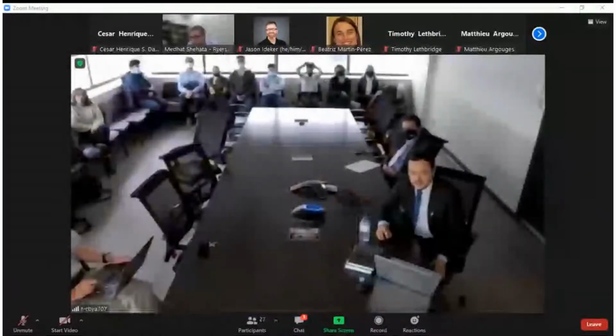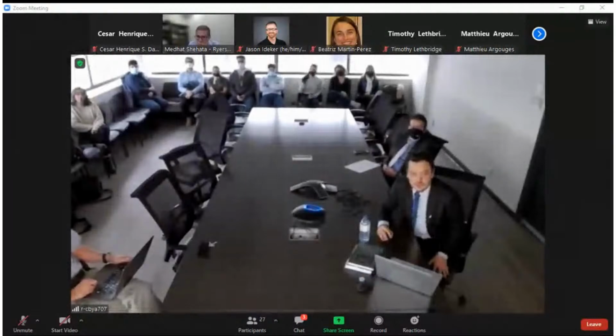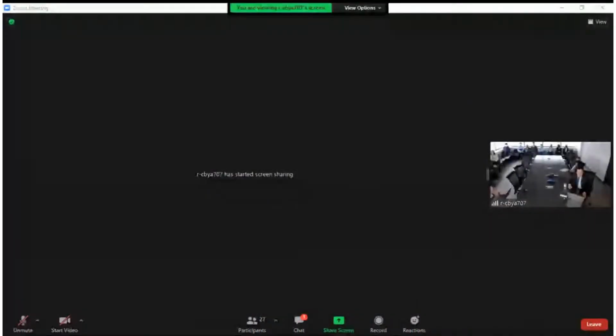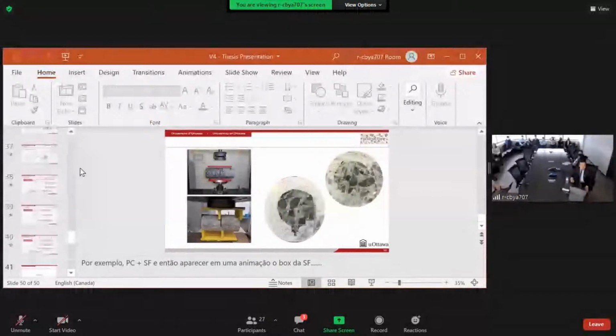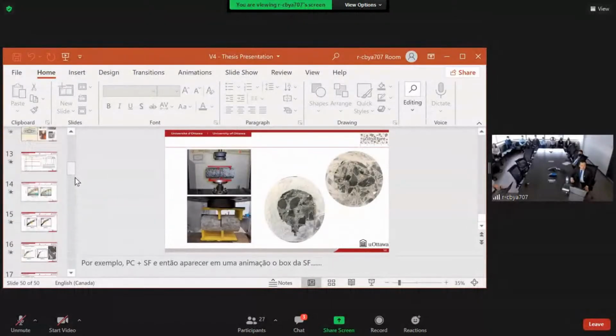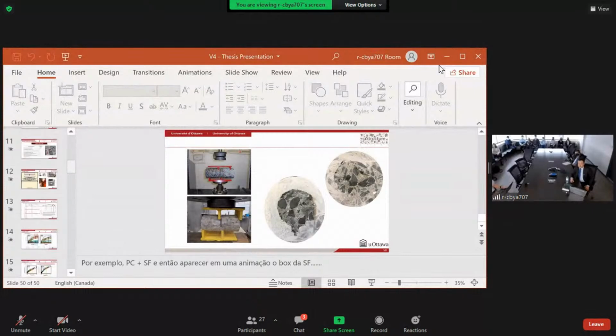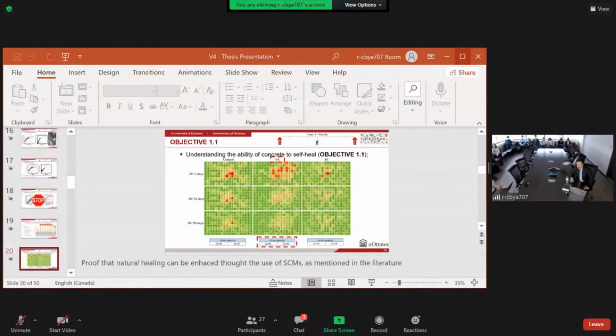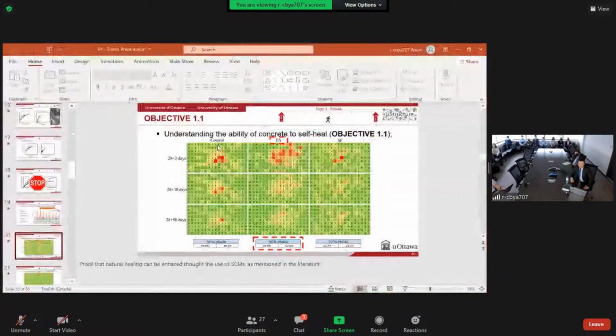Because, let me share the results again, it's going to be easier to explain. Just a second. So, for example, where is it? Here. So, as we can see, we have here just using cement. Once we crack the specimens at 28 days and after 90 days of healing, only using Portland cement with a quantity of 420 kg per cubic meter, we can see that only cement was able to heal 38% of the cracks in the cement paste.